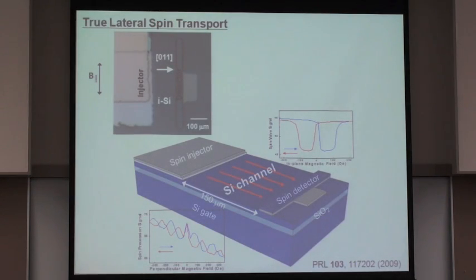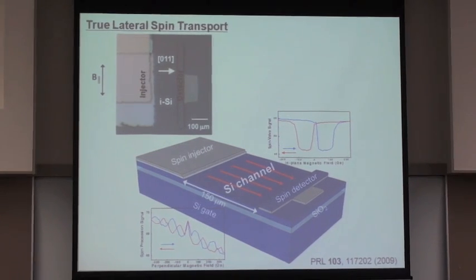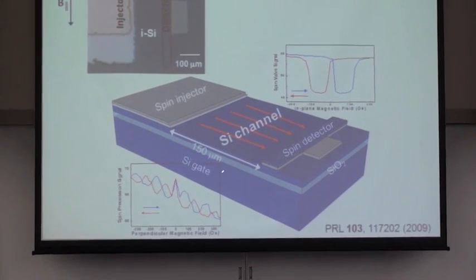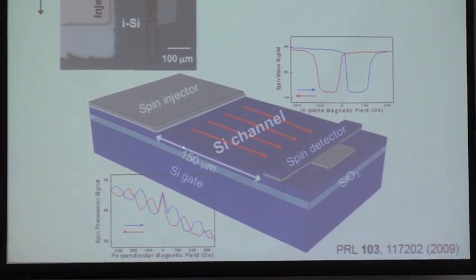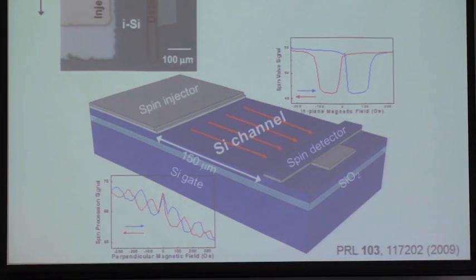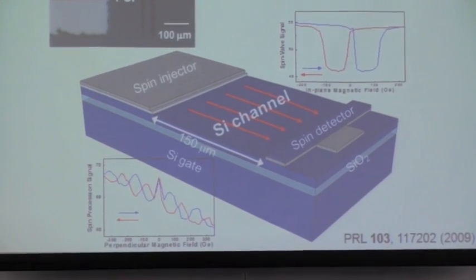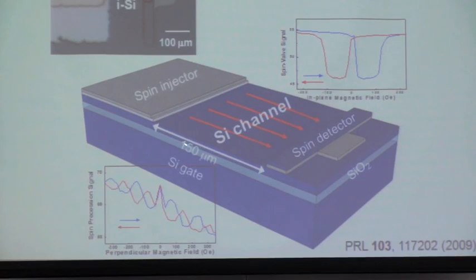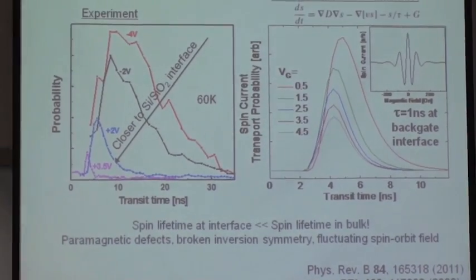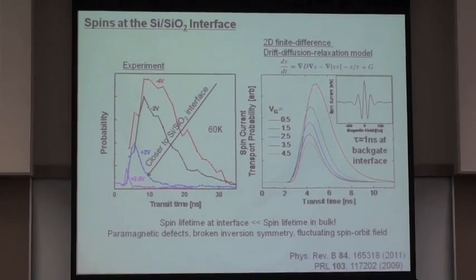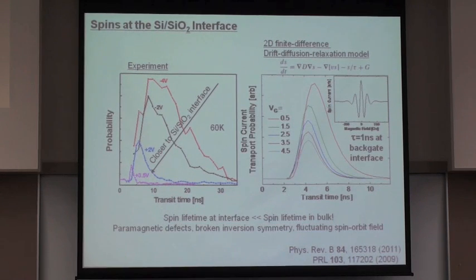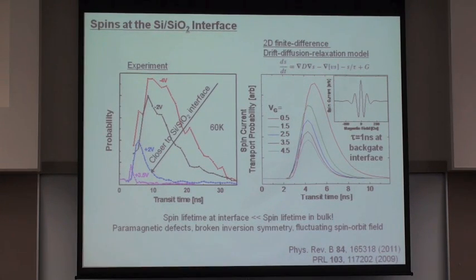I think I'm probably out of time, and I don't want to bore you, but I'll just point out very quickly that, as I mentioned, we are also able to probe other aspects of spin polarized electron transport out of equilibrium in a different kind of geometry, in which we have injector and detector which are no longer vertically oriented but now laterally oriented on the same side of silicon, so that during lateral transport we can influence their interaction with the interface between silicon and silicon dioxide below it by using the doped substrate as an electrostatic gate, pulling electrons to this buried interface. There, we see the influence of what we think are paramagnetic impurities, which are giving rise to very strong spin scattering, spin depolarization, once we pull electrons closer to the interface.